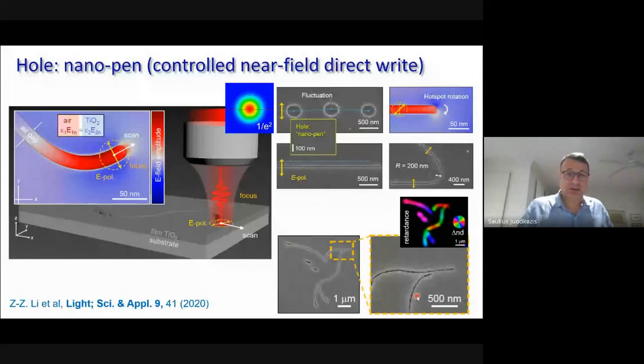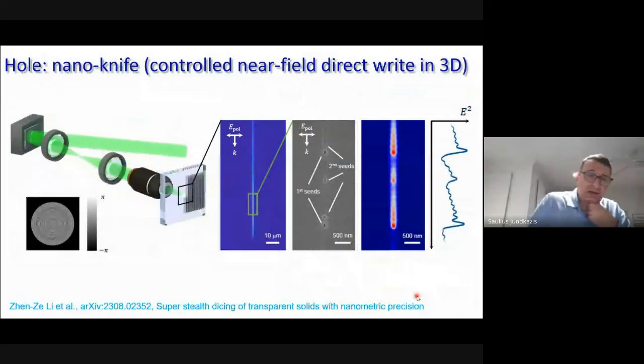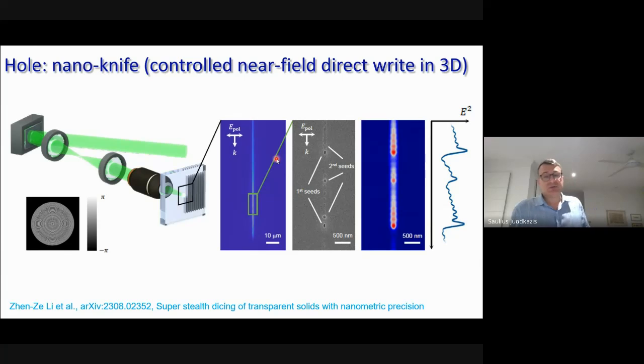So this is 2D. The latest is the 3D case. This is still on arXiv, but hopefully it will be very soon published. So in this case, we simply prepared intensity, which is a needle of light. It's kind of Bessel beam like intensity profile. So it's long light formed by a concentric type of grating on a spatial light modulator. So we are focusing this light inside glass crystal, and if we see at the threshold of damage, we recognize that there is some modification. But this is just to know that we can modify inside volume of transparent material, and this is obvious.